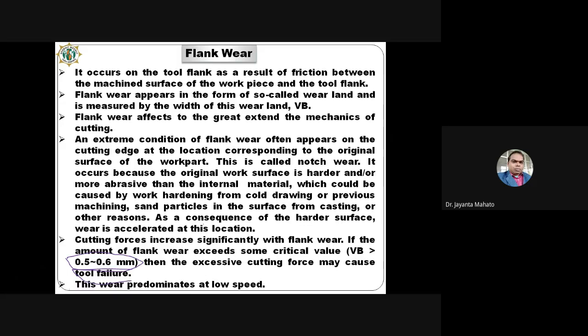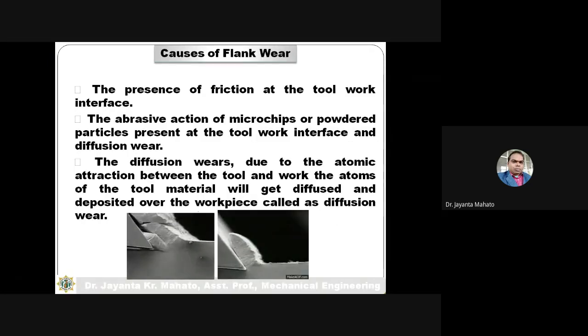This wear predominates at a low speed, meaning at low speed this type of wear can be minimized. The causes of flank wear are the presence of friction at the tool and machined work surface, the abrasive action of microchips and powder particles present at the tool-work interface, and diffusion type wear mechanisms.